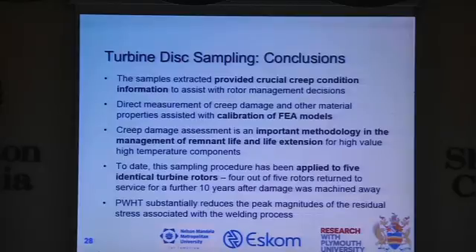The other one we had to scrap, and in most of them the creep damage was so shallow that we could machine out the groove slightly bigger, without any adverse effect to the stress within the turbines.